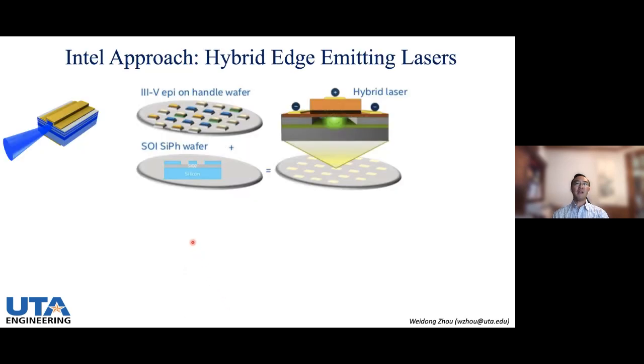Indeed, silicon photonics, among many other groups, has been very successful in addressing this issue over the last 20 years of research and major effort. They have been trying to integrate a so-called edge-emitting laser on silicon using a process called wafer bonding. The idea is basically to put a 3-5 laser material on top of silicon, and use silicon as a waveguide. You can see here, you have this 3-5 gain material on top, and they have a silicon waveguide as a laser cavity. So automatically you can form this edge-emitting laser on a silicon wafer.